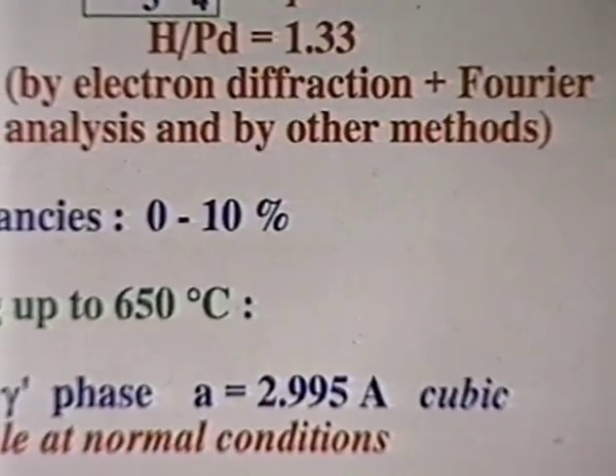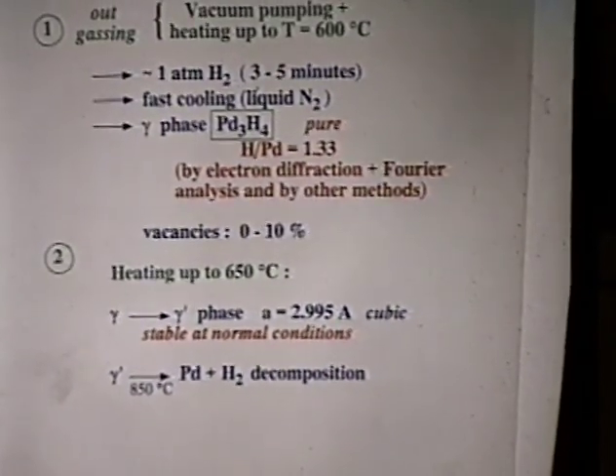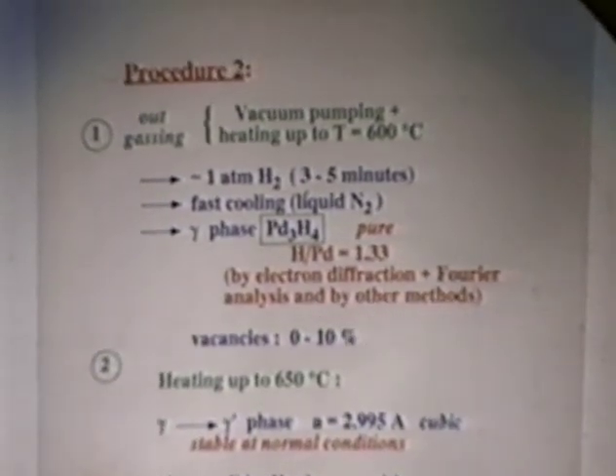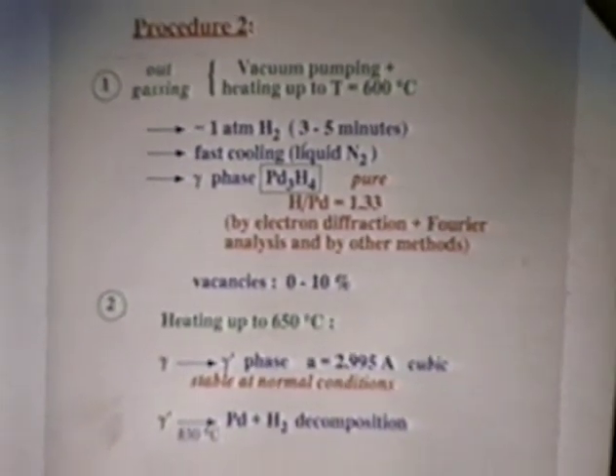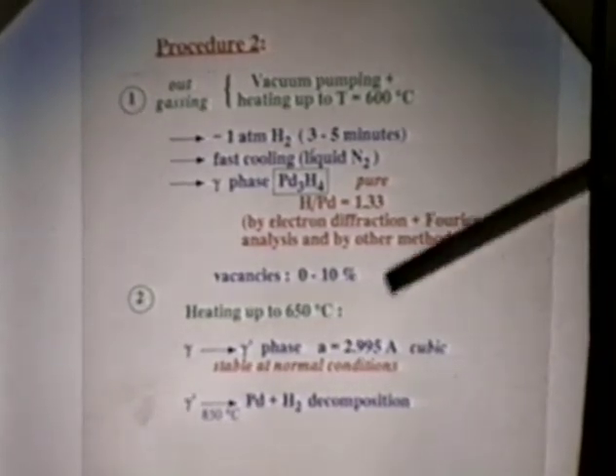Now, if you heat up this sample after having produced, by the way, the vacancies are quite small, not well known, but less than 10%. If you heat up this state, you get another phase. Here it's called a gamma prime phase, where the parameter is only one, the crystal parameter, which is 2.995 angstrom, because this is a cubic structure now, and it is very stable at normal condition.